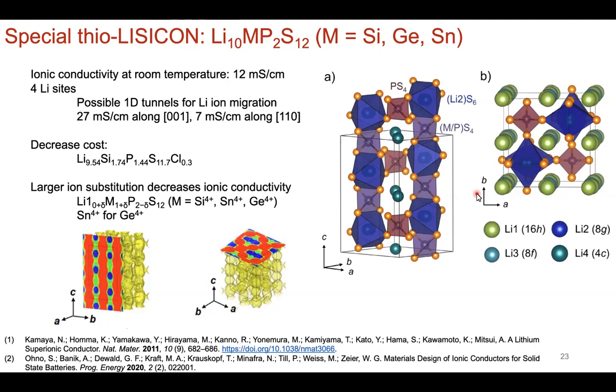So for this week, we'll continue on and talk about the special thio-LISICON. And here we come to Li10MP2S12, where M can be silicon, germanium, or tin. Of course, the compound and composition that has achieved 12 millisiemens per centimeter, comparable to that of 1 molar LiPF6 in ethylene carbonate, dimethyl carbonate at room temperature, is of course Li10GeP2S12. So that's very exciting.